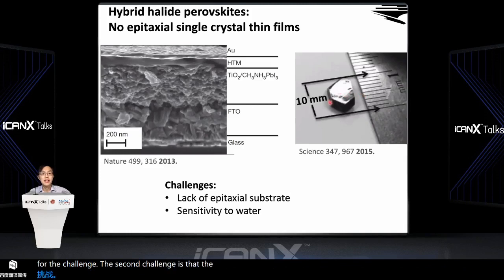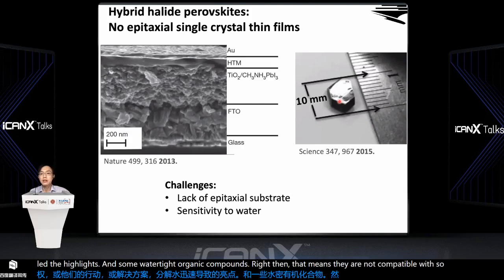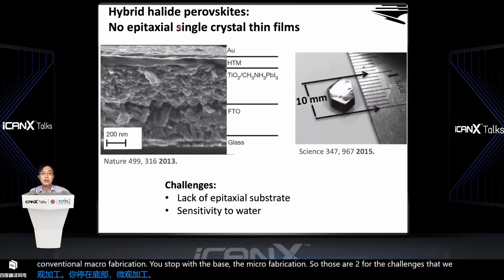The second challenge is that this organic-inorganic halide perovskite is very sensitive to water. That means if you immerse them in any solvents or water-containing solvents or etchants or solutions, they will decompose very quickly into lead halides and some volatile organic compounds, right? Then that means they are not compatible with conventional lithography-based microfabrication. So those are the twofold challenges that prevent people from making epitaxial single crystal thin films of this material.